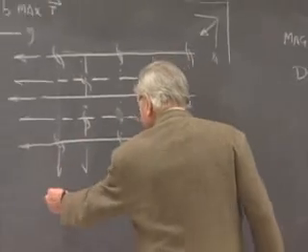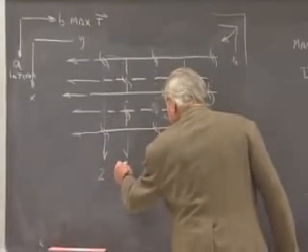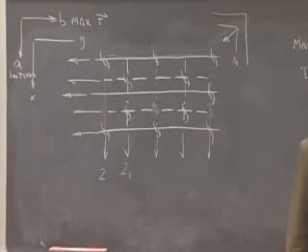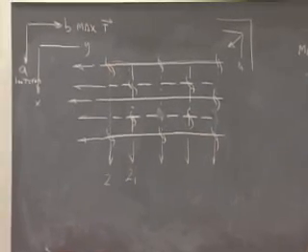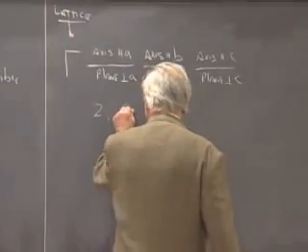But we've got another problem. If we look at the axes, if any, that are along A, we've got this symbol that stands for a two-fold axis and this single barbed arrow that stands for a 2 sub 1 screw. So what kind of axis is along A? There are two different kinds of axes. So in here, we could put either a 2 or a 2 sub 1.